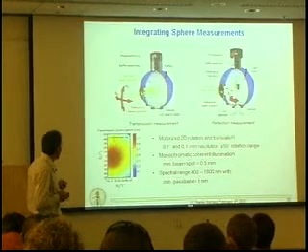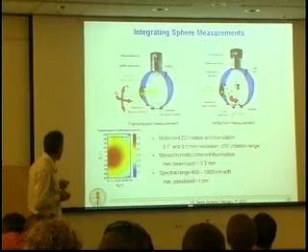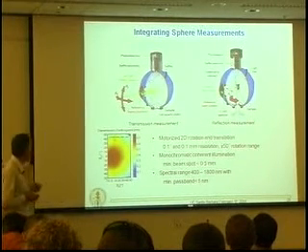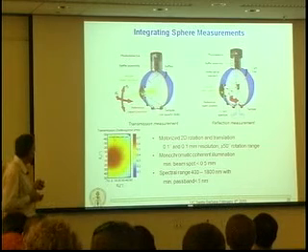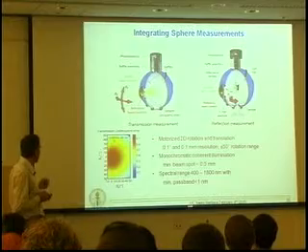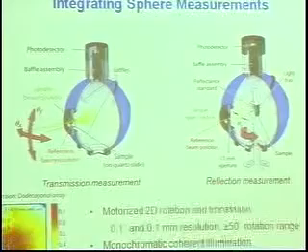So we're interested in determining whether or not there's a substantial light absorption. Is there as much absorption as there would be in a solid substrate? To do the measurements, we use integrating sphere measurements because we're interested in both specular and diffuse measurements. To measure absorption, we measure both reflection and transmission and measure absorption from 1 minus reflection minus transmission.